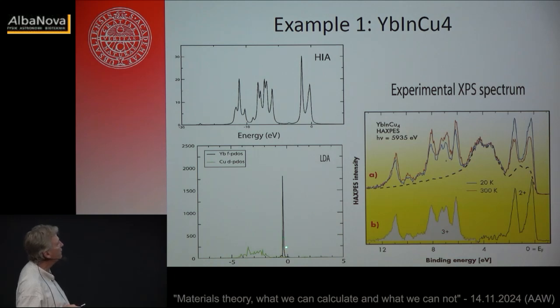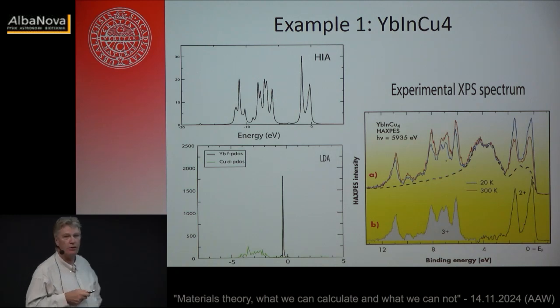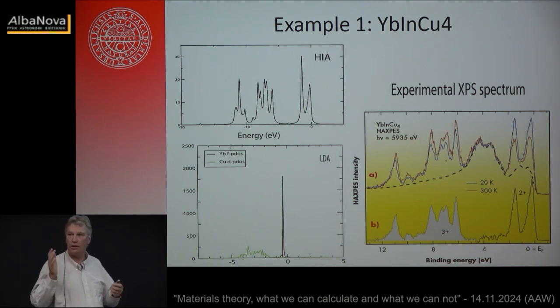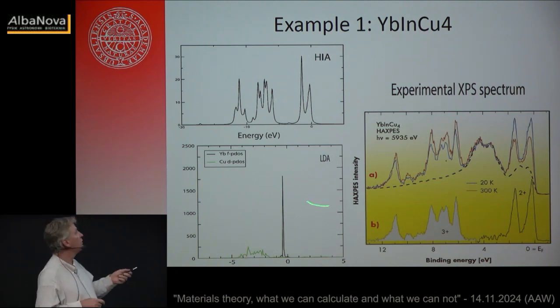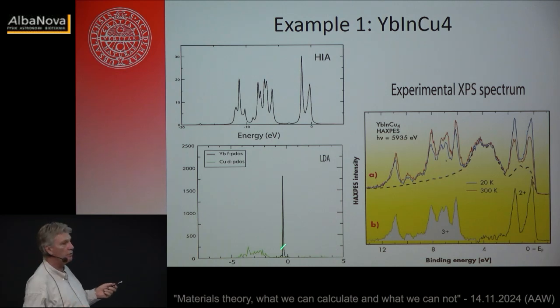But DMFT then tweaks this narrow peak into what you have up here. So this is DMFT in a particular approximative way to do it. And so you have the two-peak feature here. You have things that go down to 12 eV. You have a gap in between. You have 3 guys here. It actually looks pretty good. It certainly fixes things up much better than just looking at this and saying, we don't know how to do this.